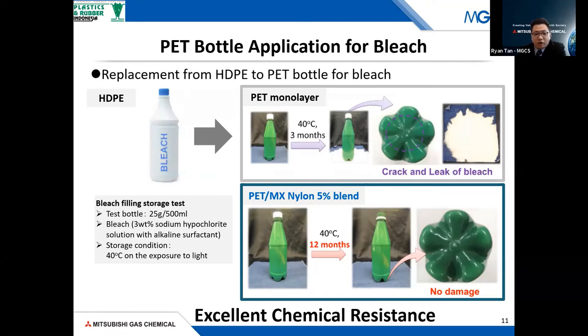So let's look at the original PET monolayer. At 40 degrees, 3 months, the bottles actually cracked and bleach leaked out. But when you compare it to 40 degrees for 12 months, there was no damage in our test with the customers.